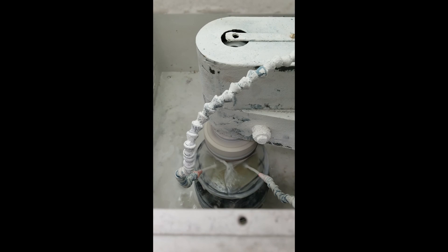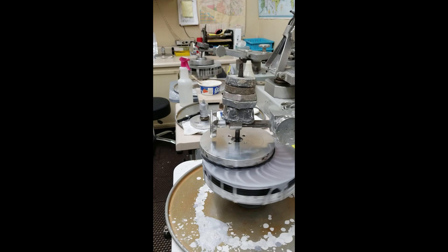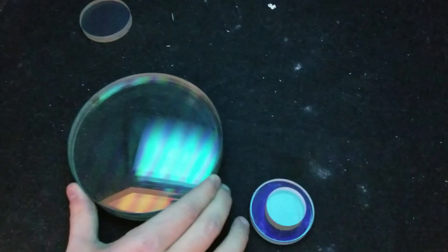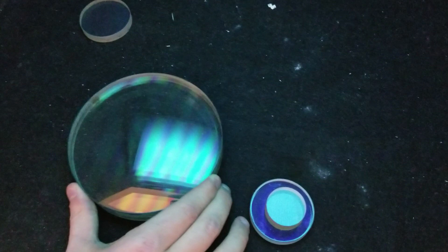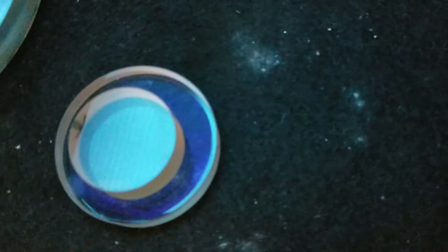The piece is then polished down to approximately the right curvature using various machines. When the surface is very close to the right curvature, they place it on top of a test surface and look at the interference pattern to inspect for imperfections. This is their simple Fizeau interferometer.